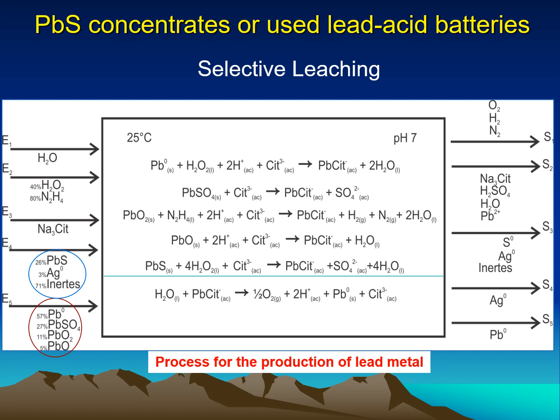And the soluble complex that's produced in all four cases is lead citrate, which is soluble at pH 7. In the case of galena concentrates, and this is a very selective reaction, galena reacts with hydrogen peroxide to form also soluble lead citrate. Once we have our leaching done, the pregnant solution is sent to electrolysis, a very selective and efficient electrolytic process, which uses electricity to form lead metal, and at the anode, we form oxygen from water.